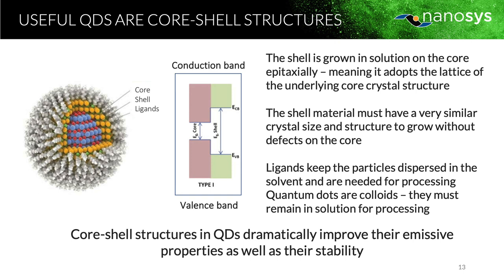What this does is prevent problems from the dangling bonds on the edge. Remember, quantum dots only have maybe hundreds or thousands of atoms, and a significant fraction of them are on the surface. If those all have unfulfilled bonds, these result in low energy states. This is problematic for good optical properties. So growing a shell around it is really important. And the shell should have a higher band gap. Otherwise, this exciton wouldn't be confined to the core. You want to keep that excited state in the core of the particle.